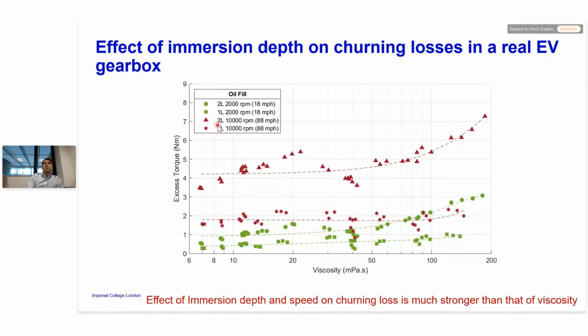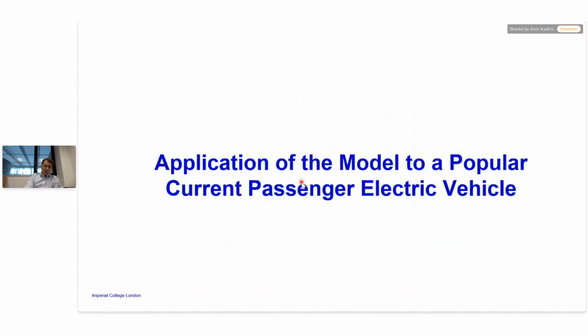So you've got 1 liter and 2 liter fill of the gearbox. 2 liters is really what it's filled with. And you can see this is the churning loss here for the 2 liter, and this is for the 1 liter. Big increase, double. So the effect of immersion depth is much more pronounced than the effect of viscosity. The trends we see in terms of churning loss versus viscosity are the same in both our lab rigs, with a single gear and a full electric drive unit.